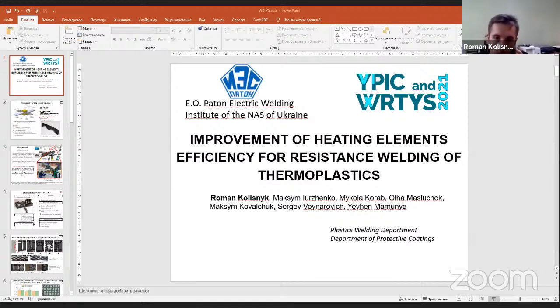In this work, we used two types of polymers: high-density polyethylene as a model to evaluate the efficiency of this technology, and the high-tech polymer polyaramid, which is widely used in the aircraft industry. Metal mesh heating elements were made from stainless steel mesh and titanium mesh. The surface of this element was modified by chromium, steel, molybdenum, and titanium. Heating element made from electroconductive composite was made from high density polyethylene and was filled with carbon black and carbon fiber.